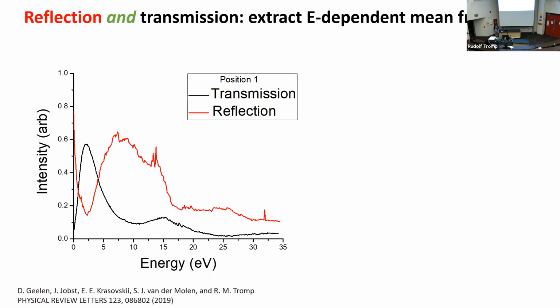We have, and these are absolute numbers, in this case, a transmission of 0.55 or so, a reflection of 0.15, and so there's a little bit missing. That's the inelastic piece, right? You have the two elastic channels, and whatever does not add up to one, that's the inelastic channel. So we have the inelastic channel, we have both the elastic channels.